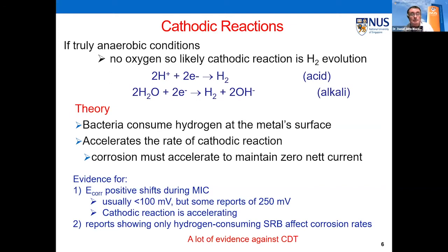We do see ennoblement. The Ecorr, when you have MIC, does move positive, usually by less than 100 millivolts, but there have been reports of up to 250 millivolts. So that tells you that the cathodic reaction is going faster. And there are some reports showing only hydrogen-consuming SRB affect corrosion rates. But there's quite a lot of evidence against this CDT.